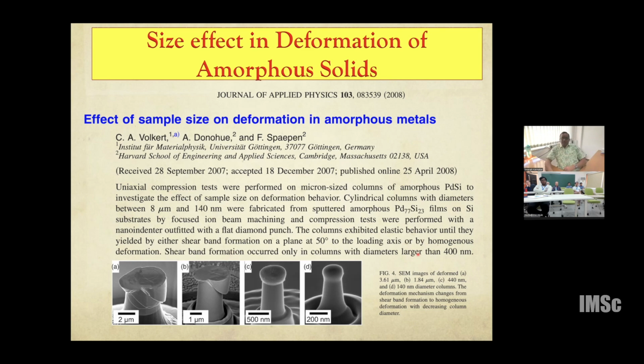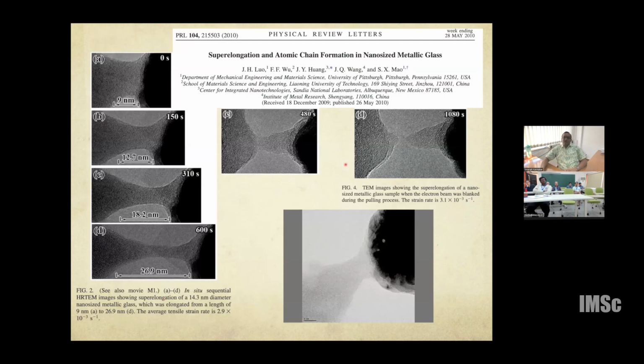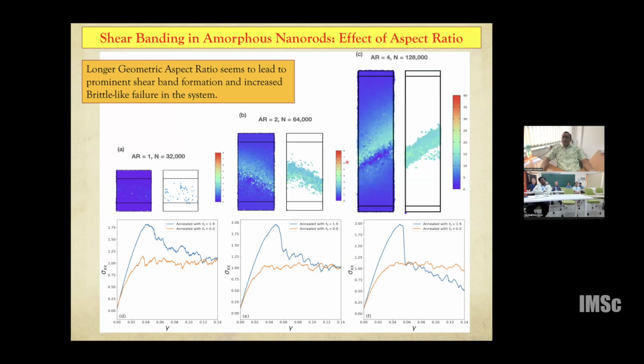This has been in the literature for quite some time: if you take nano pillars and deform them, and the pillar diameters are smaller than around 100 nanometers or so, then you get deformation which is more homogeneous, like this bulging type phenomenon. But if your samples are thicker, then you can get very clean shear bands. Something similar has been shown in this paper as well. As you go to very, very small nano pillars of metallic glasses and pull them, you can get shear bands and very thin neck formation. So we looked at something similar in our simulations.